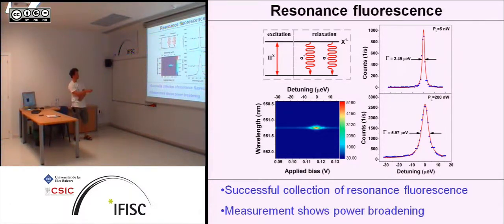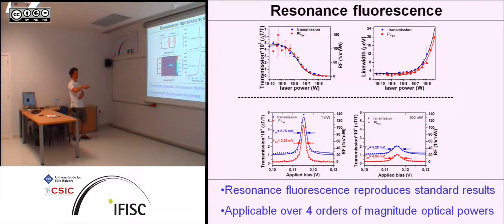And here we see a scan. We again have the laser at the constant energy. This is the line of elevated counts here. And then we tune the quantum dot through the resonance, and here the resonance hits, and this basically is the spectra of the collected quantum dot emission. And if you now cut through this, you can see here at the low power this spectrum, and at higher power you already see the power broadening.